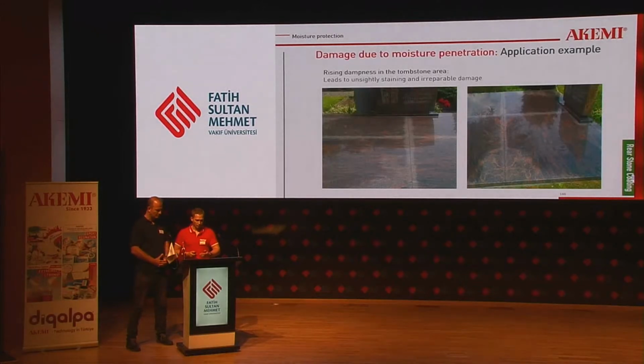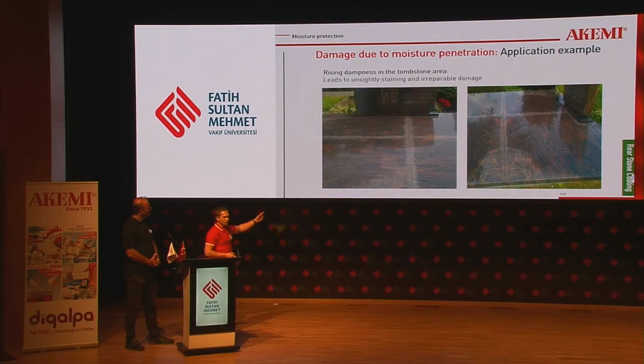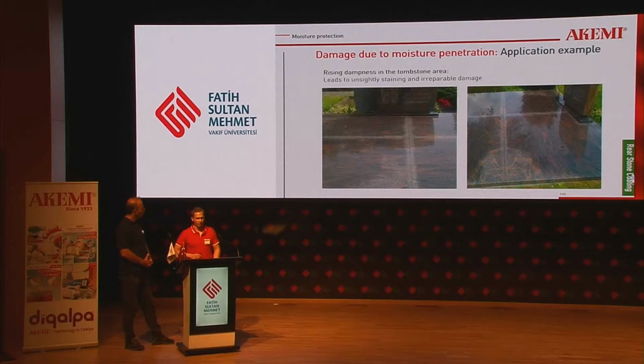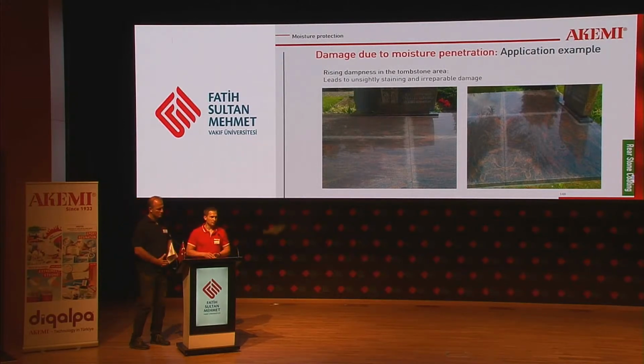And I can show you something. This is a gravestone area in Germany. And the only thing you can see near the joints is the original stone. The other side of the stones is the stain. So it's completely stained, and it's hard to clean that again, because there come lime residues from the side, and they damage the stone from inside, and you cannot clean this anymore.